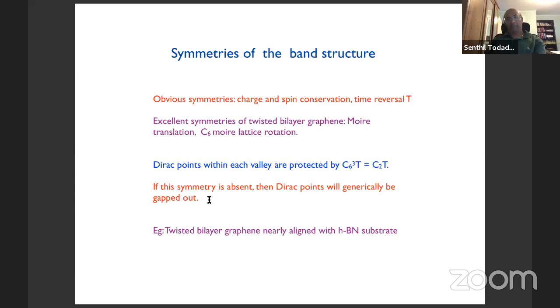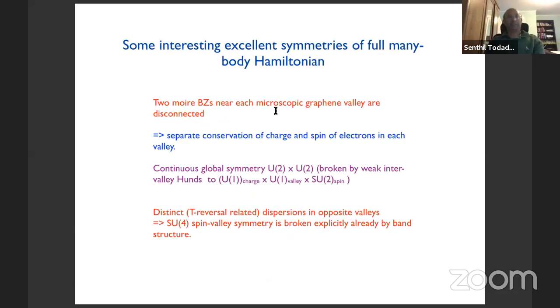Now, experimentally, a way to break C2T symmetry is to take twisted bilayer graphene and align it to a boron nitride substrate. Since boron nitride breaks C2, the alignment with boron nitride leads to an effective Hamiltonian that breaks the C2T symmetry. And then theoretically, you expect that charge neutrality becomes insulating. And that's basically consistent with experiments that have been done on this system. Okay, so that's about band structure.